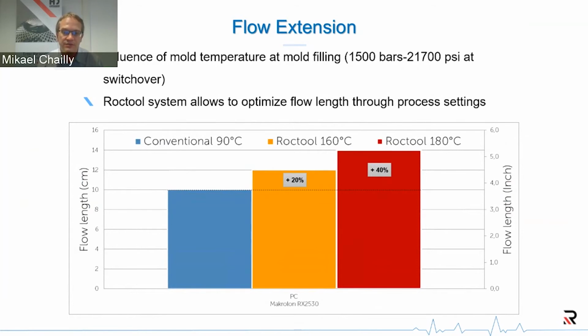But we can totally adapt the process settings, and possibly go up to the melt temperature, but keeping reasonable values, we could for this PC go and use a mold surface temperature at 180 degrees C, and then this flow length would extend up to 40%. So just adding an additional 20 degrees on the mold surface, you double the gain you can expect. With this ability to do this only through process settings, you have the ability to optimize whatever flow length gain you would have, and of course it would also impact the cycle time. So it's just you can choose whatever best compromise you want through process settings.